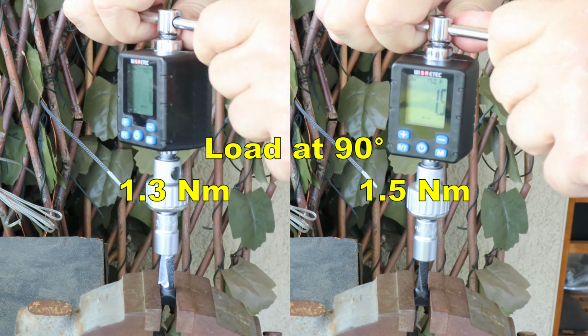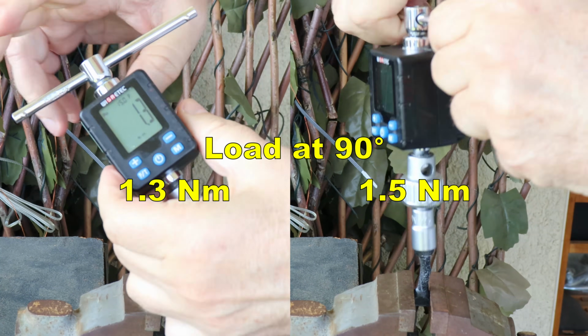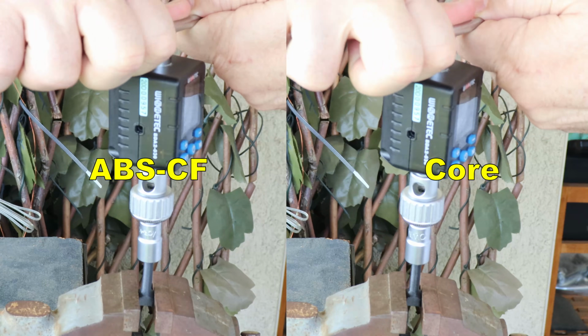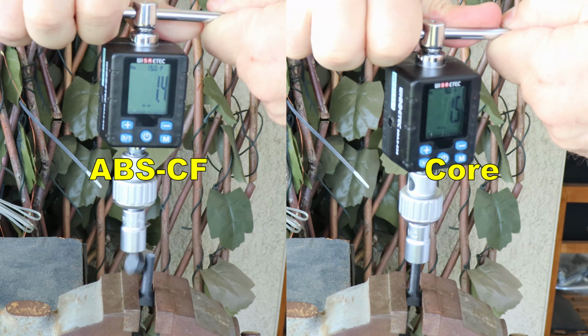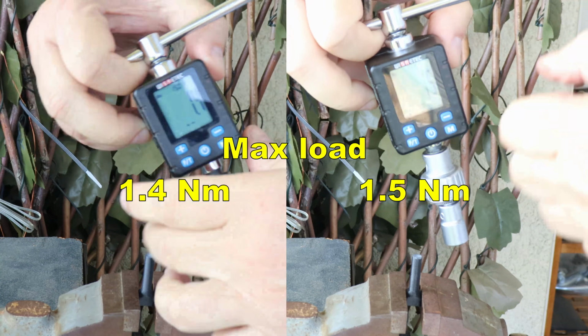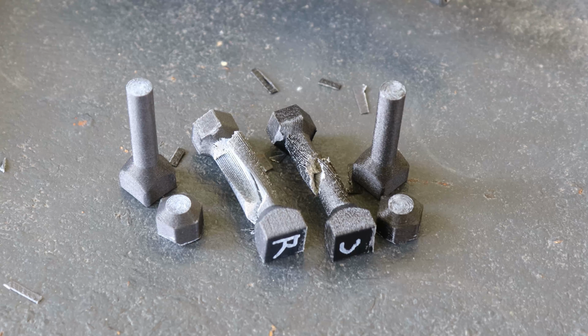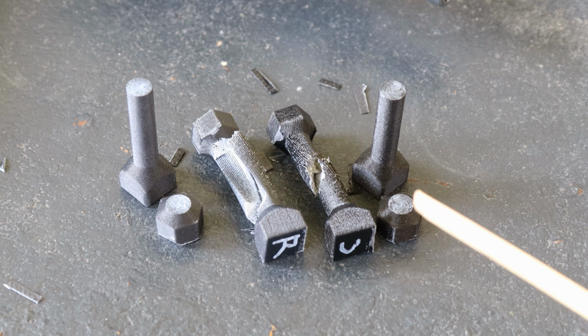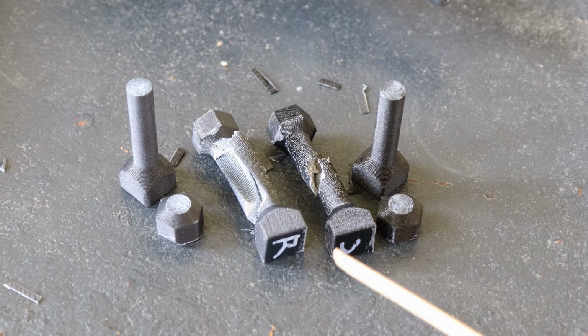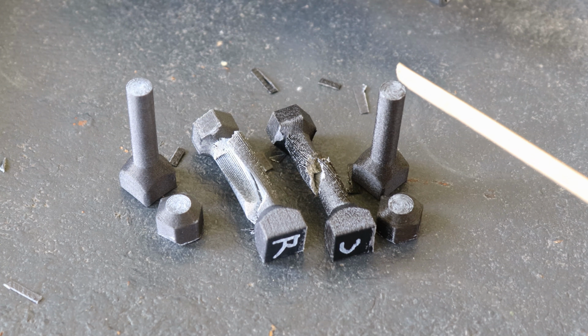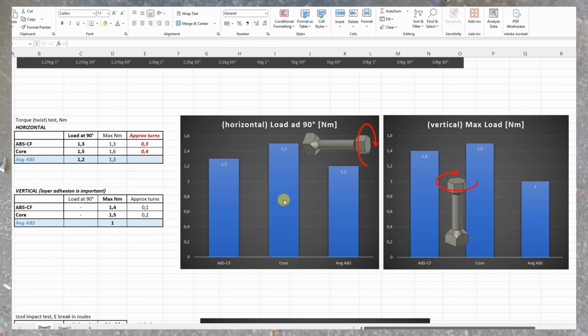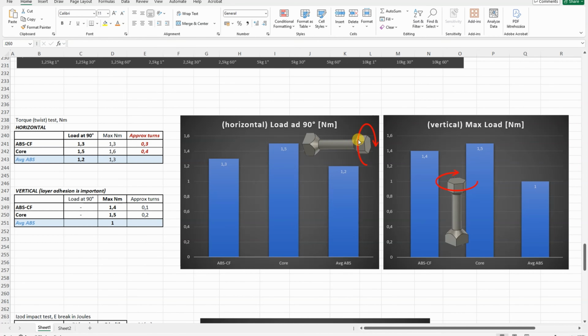1.3, 1.5, 1.3, 1.6. 1.4, 1.5. No big surprises here, but it was really nice to see that I could make almost 90-degree rotation with these vertically printed test objects from the core version. Both carbon fiber materials are stronger compared to the average ABS, non-reinforced, and the core was the strongest between these two.